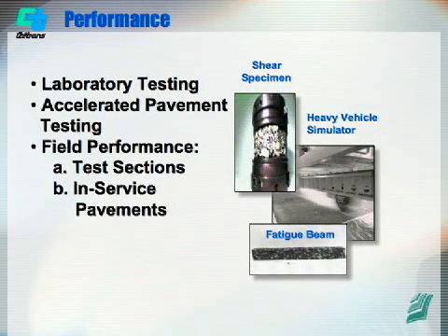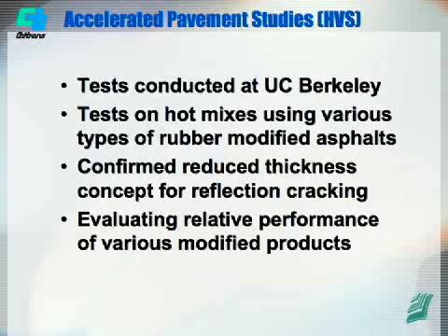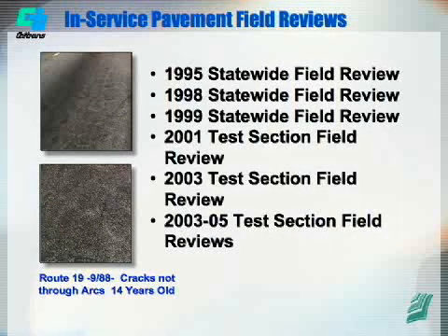Many of the tests over the years, since 1992, when we developed the reduced thickness design, we've done validation tests using the accelerated pavement testing program and using shear testing and fatigue testing and in-service pavements. We've looked at the rutting, fatigue behavior, reflective cracking, and moisture sensitivity. We've done an extensive research program to evaluate these materials. And we have confirmed the reduced thickness design concepts through field tests and through the heavy vehicle simulator. We've done surveys statewide. We have many projects in every district under different climatic zones.